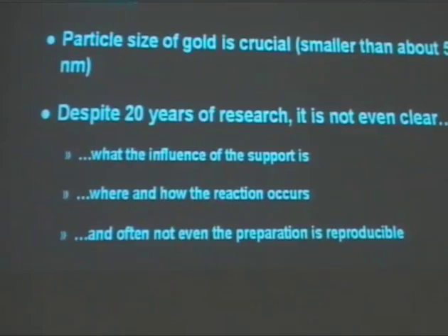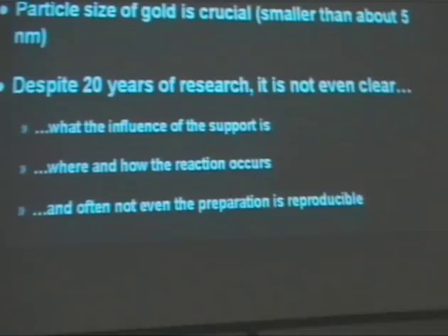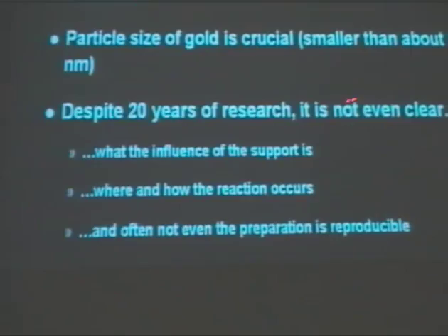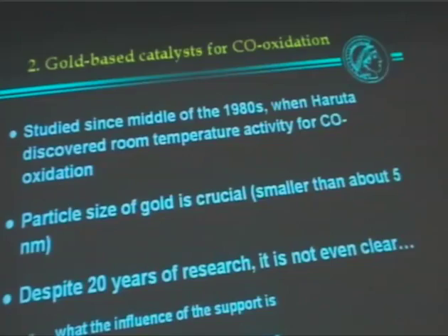particles small, support them on the correct support material in the right way, they oxidize CO at very high rates, even at room temperature and below. Particle size of the gold needs to be preferably 5 nanometers or below, but I think one would have to say that despite 20 years of research, this was the middle of the 80s, now we are the middle of the 2000s, it is not clear what the influence of the support is, whether there is an influence of the support.